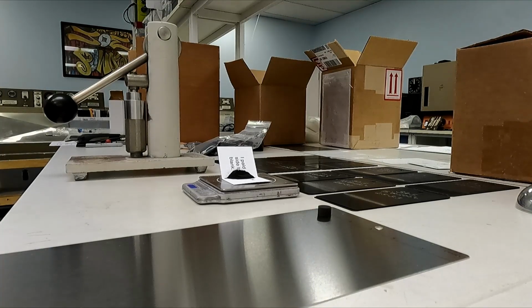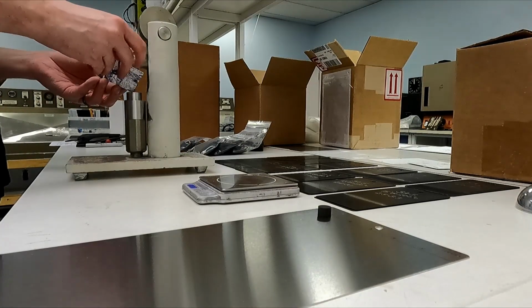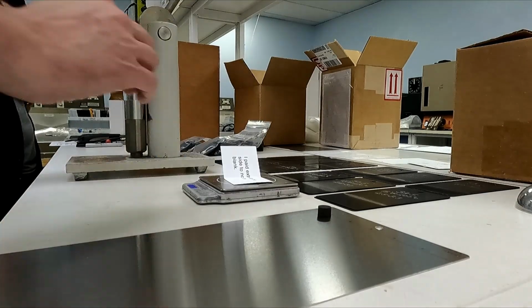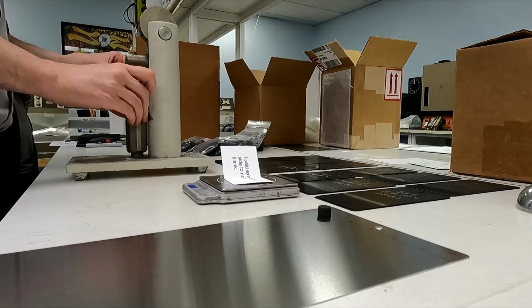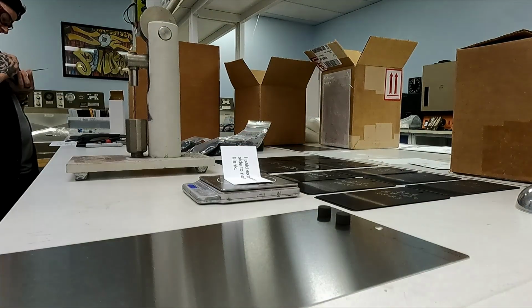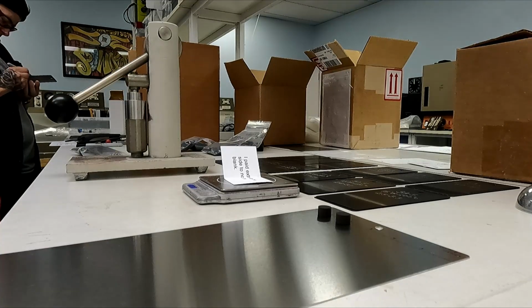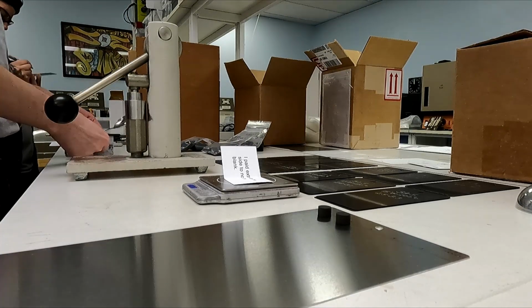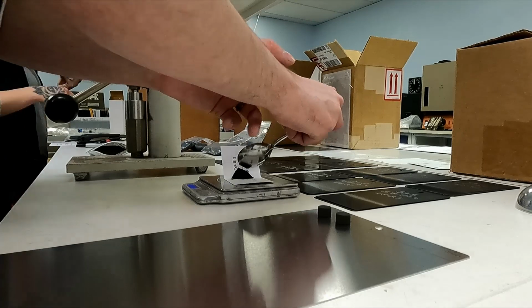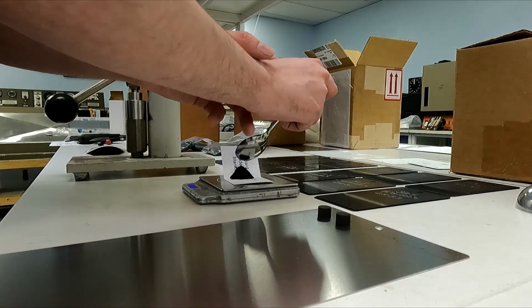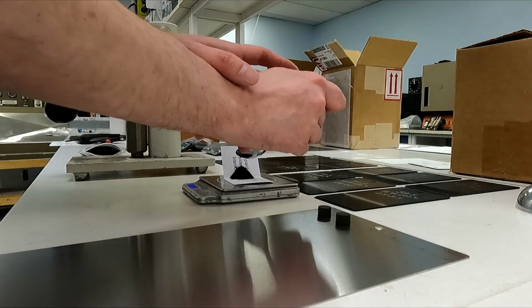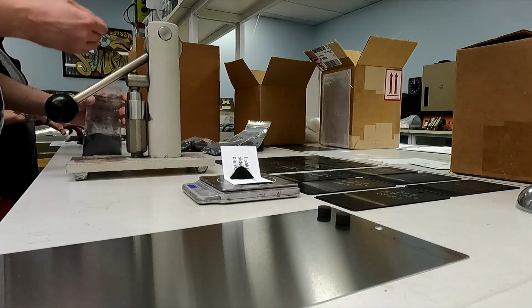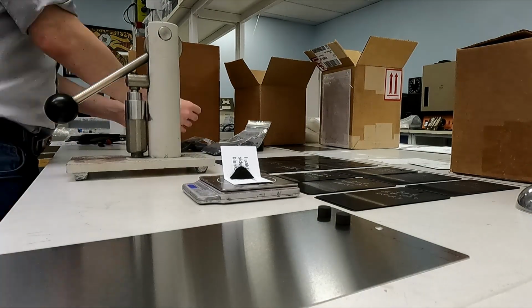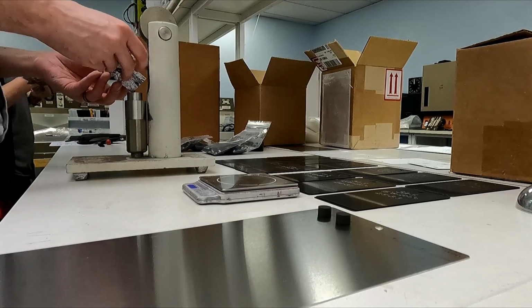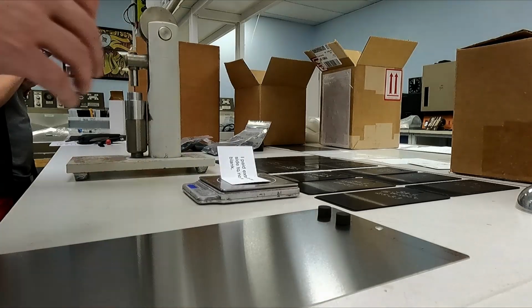But first, let's talk about how to run the test. A pellet press conforming to the ASTM standard is used to form an amount of powder into a solid cylindrical pellet of a standard size. The test method suggests the amount of powder be 1/2 in grams of the powder's density or specific gravity. In our lab, we typically use 1 gram of powder, although in some comparisons it does make sense to use different weights for the pellets that are calculated to give them equal volume rather than equal weight.